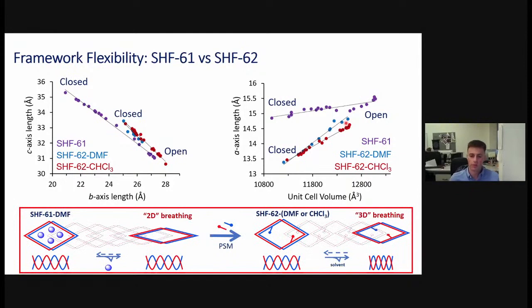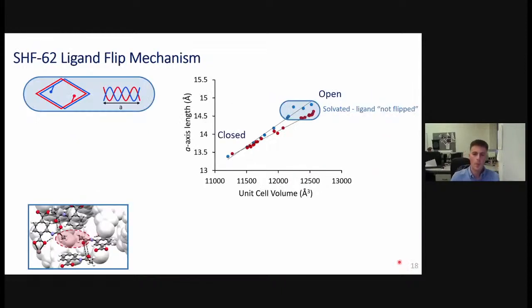So essentially what we've done is modifying the framework. We've gone from a material that breathes in 2 dimensions, so just the B and C axis associated with the pore width and pore length, through to modification where we now have breathing in 3 dimensions. So we have a change in the B and C axis associated with the pore. Also, this helical-like arrangement undergoes a compression. And there's quite a neat little mechanism that allows this transition between the two-dimensional and three-dimensional breathing of the framework material.